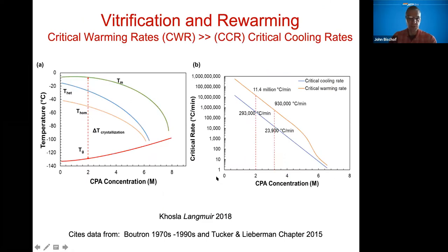And this is just looking at that from the point of view, again, of a phase diagram on the left. And it kind of explains one of the problems, both on the way down and the way back up, as you drop below the liquidus and you're trying to get to the glassy phase, especially when you're at low concentrations, you have this huge window of temperature that you have to traverse to get there. And so you're going to have to do that twice, once on the way down and once on the way back up. So that's a huge barrier.